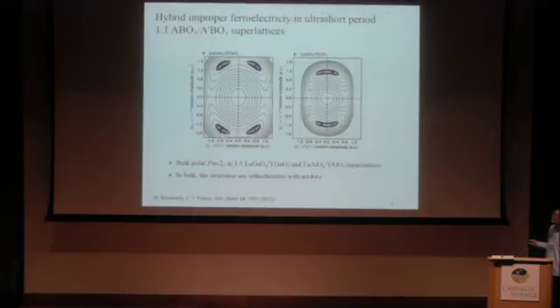From this table, we found with small tolerance factor, the polar to nonpolar transition can occur in both compressive and tensile strain. But with increasing the tolerance factor, only the compressive strain can trigger the polar to nonpolar transition. And we also found that the polar to nonpolar transition can only occur in a range of tolerance factor as shown here. And it's very exciting that the PBCN phase in the bulk strontium zirconium oxide has recently been found at high temperature in experiment, which is consistent with our prediction on the temperature dependence of the stability of this PBCN phase.